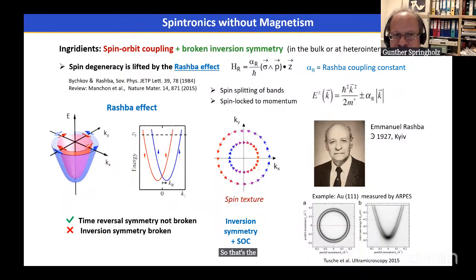So that's the reason why, for instance, graphene, which is a light element, just carbon atoms, has a very small spin-orbit coupling. As you noticed here, lead telluride, for instance, lead is a very heavy element, so that certainly helps in having a large spin-orbit coupling, and this spin-orbit coupling enters into the Rashba coupling constant. The larger the spin-orbit coupling, the larger the Rashba constant will be. But it's not the only factor. Also the degree of symmetry breaking, or how the symmetry is broken in the system, plays a role that determines the magnitude of the Rashba constant.